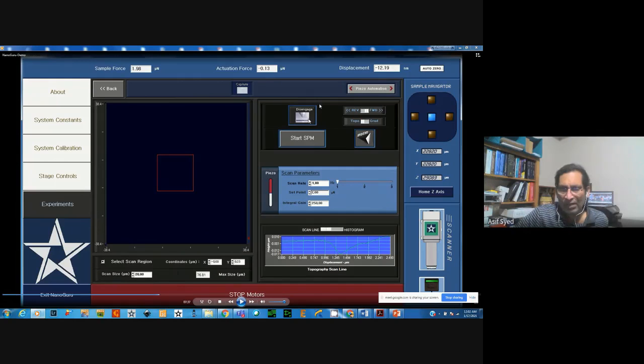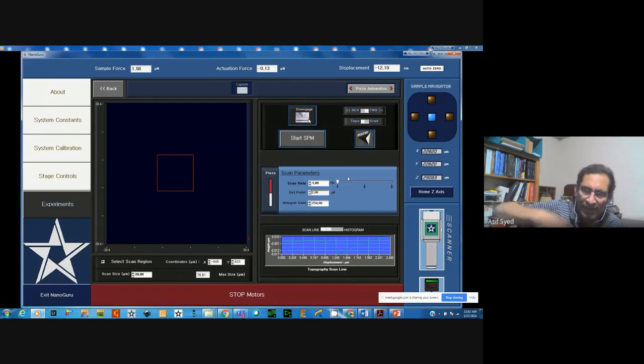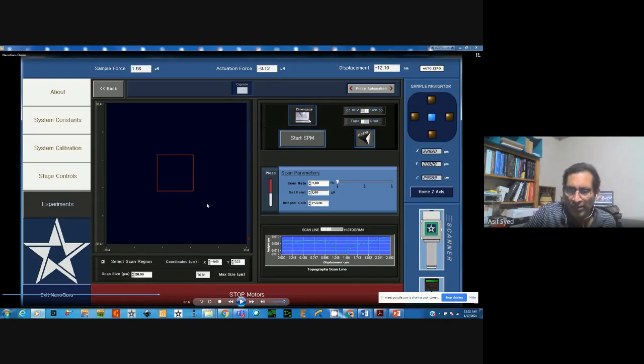On this side of the interface, you have a couple of buttons: disengage and engage. If you want to momentarily engage or disengage the tip from the surface, you can do that by activating that button. And then below that, you have scan parameters. This is basically how fast you want to scan. We can go up to 10 hertz scanning. It depends upon the size of the image that you want to do. When you do 20 micron, the maximum scan rate is about 3 hertz.